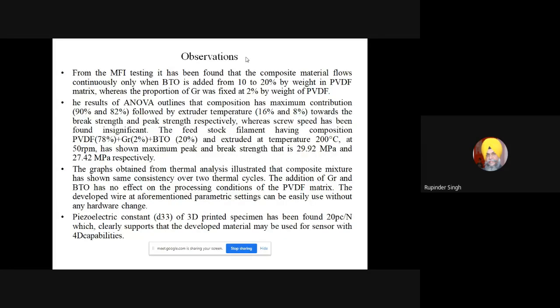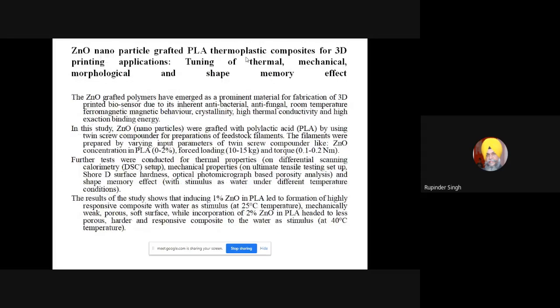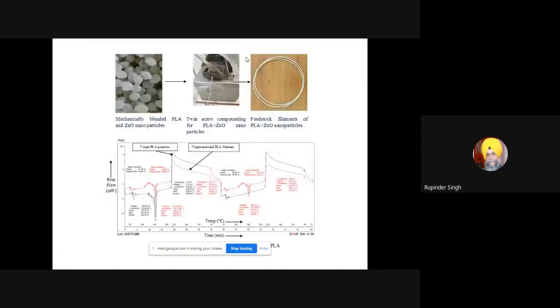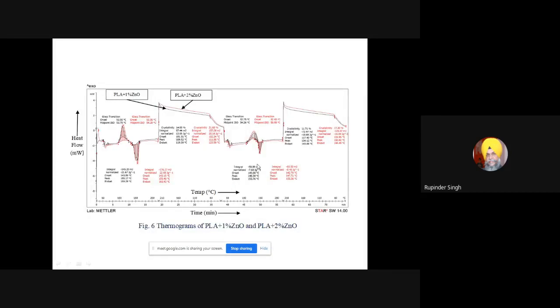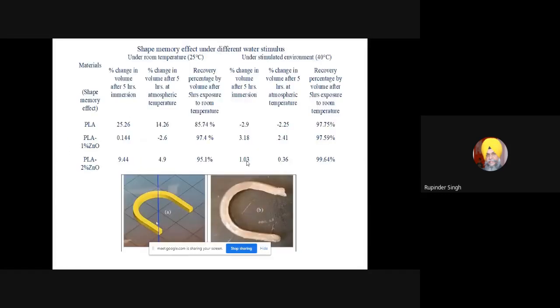So finally, at the end, before I conclude, this last thing that I want to discuss with you: in a single step, have some polymer with some type of reinforcement, like in this case ZnO was reinforced, wire was prepared, feedstock filament, doing some thermal analysis depending upon the composition. Now what we did is we printed a U-shaped component, then we tried to see the effect of the temperature and the water together. So we tried to see the two stimuli.